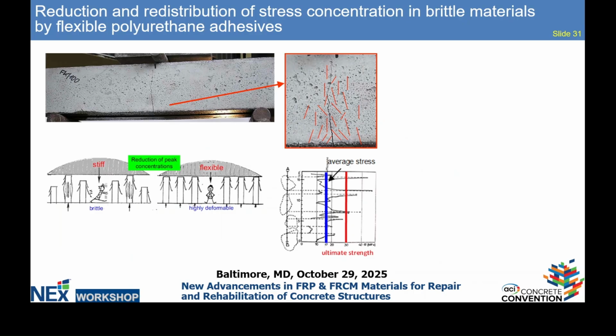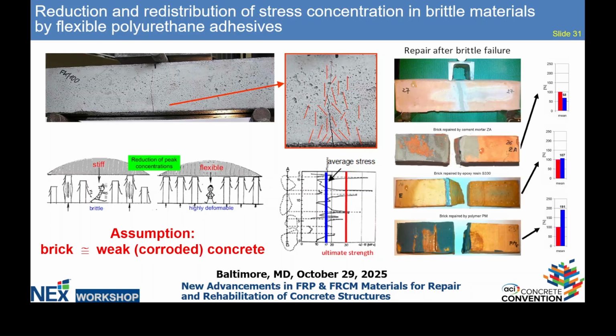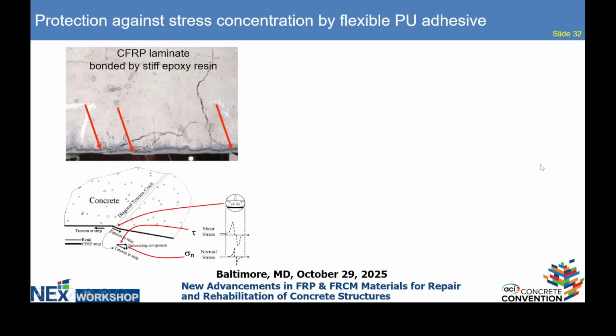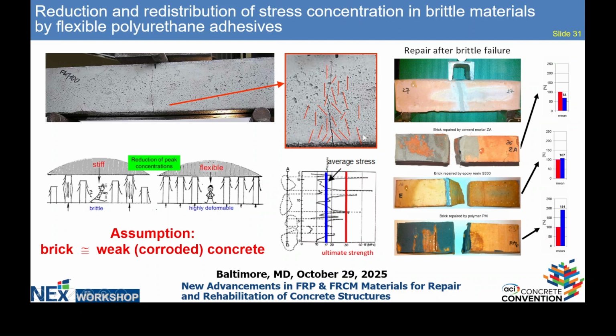So when we have the mineral mortar or mineral concrete, the crack starts due to micro cracks, due to stress concentration here. When we redistribute the stress more evenly, we can reduce this stress and also increase the capacity of the structure. So let me assume that the corroded weak concrete is a brick. This is the brick that was damaged in 4-point bending, so repair with cementitious mortar. We don't recover the original strength of the brick. When we bond it with epoxy, we increase only 7% due to this zone with micro cracks. When we bonded it with flexible polyurethane, we recover 90% of the total strength. So it is better to break the brick, rebond it, and use.